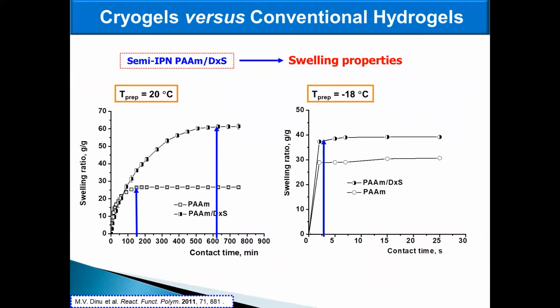The investigation on the swelling experiments of gel with or without entrapment of the dextran sulfate, regardless of the preparation temperature, showed that the semi-IPN hydrogels have a higher swelling ratio compared to cross-linked polyacrylamide gels due to the hydrophilic character of dextran sulfate.